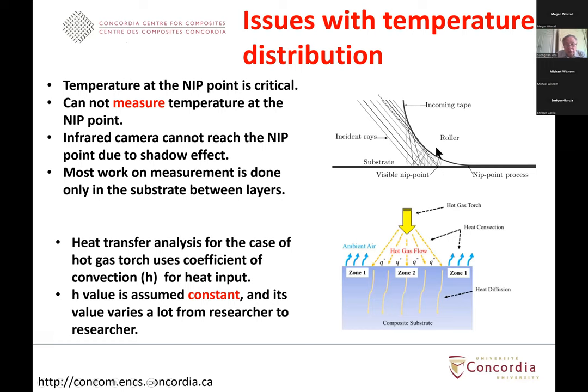But the fact that you have the roller, and the roller has some kind of a boundary here, it seems to obstruct the line of sight of the camera. So that means the camera cannot reach the location of the nip point. So in that case, people cannot measure the temperature at the nip point. We can only measure temperature around that, but not at the nip point. But the nip point is very critical for understanding bonding for the thermoplastic composite. So that is from the measurement side.